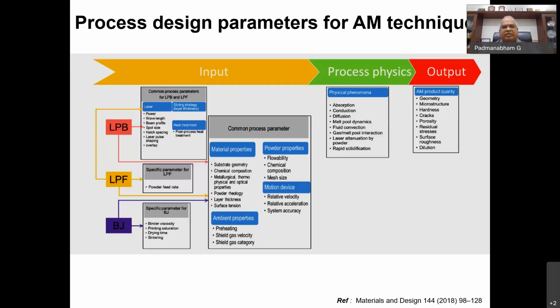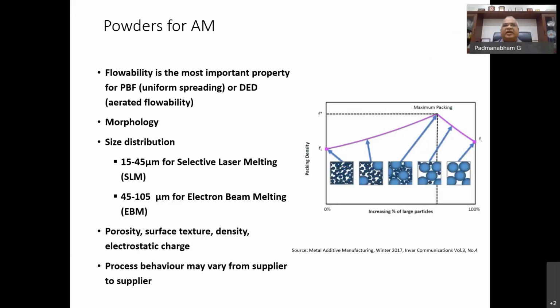I'll give you a couple of examples also of how it affects. The first one is the case of material itself. Why is it so critical? Whether it is powder bed, where we are spreading a layer of powders, or we are blowing the powders in the case of direct energy deposition, the flowability of the powder is very important. So that is the first parameter, and that comes from the morphology of the powders. So we need spherical powders.